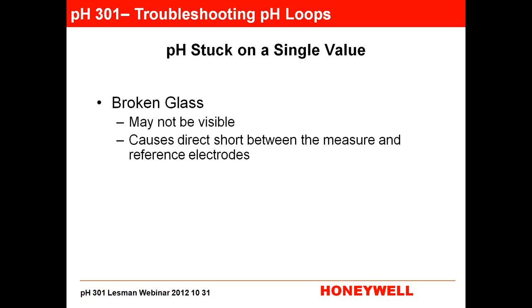If you're using a glass measuring electrode, it is a pH-sensitive glass that is annealed or welded to a Pyrex stem. And that stem is completely surrounded by the reference solution and the reference electrode. So if you get a crack in that glass inside the sensor, it will develop a very slow leak. And when that finally gets connected, you're connecting the reference to the measuring electrode, and it will stick. It will many times stick someplace close to 7, but not always. And as I said, a lot of times you can't see that, but there are some electrical checks you can do.